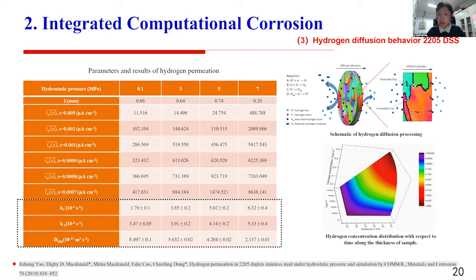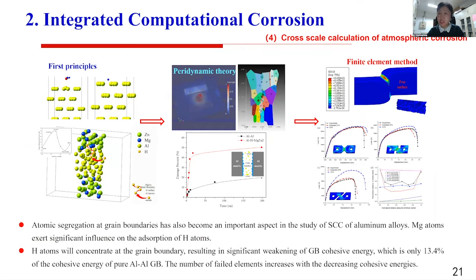After that, we use the COMSOL software to establish and simulate the hydrogen diffusion inside the stainless steel. So after that, we can get different kinds of boundary conditions for the hydrogen concentration, to get the hydrogen concentration distribution with respect to time along the thickness of the samples. And for the time limitation, this part is just very fast to get.